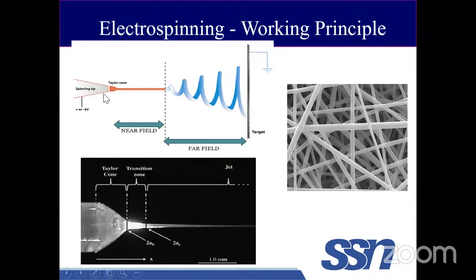So this is what is going to happen, where we have the spinning syringe tip, and the infusion pump is going to pump the polymer solution, where we will be applying the high voltage, right? As the potential exceeds the surface tension of the polymer, it's going to form a Taylor cone first, and there is a stable near field. At the far field, these fibers will start whipping. At the collector end, it is being collected as a fiber, right? This is how we will be seeing those fibers under SEM, scanning electron microscope, right?